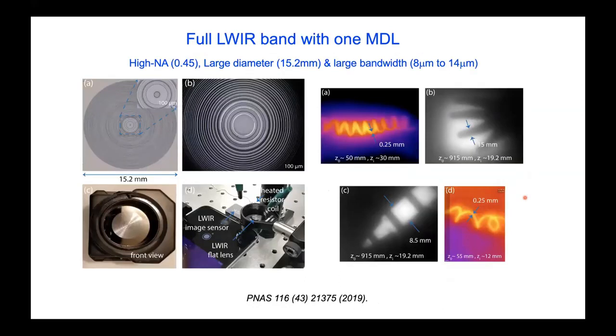Of course, these ideas are not limited to visible or near infrared. We're agnostic to the band as long as there are materials that are transparent. So this is an example in the long wave infrared, which we demonstrated a couple of years ago, where we had relatively high numerical aperture, 0.45, relatively large diameter, a little more than half an inch, and a pretty big bandwidth going from 8 to 14 microns.